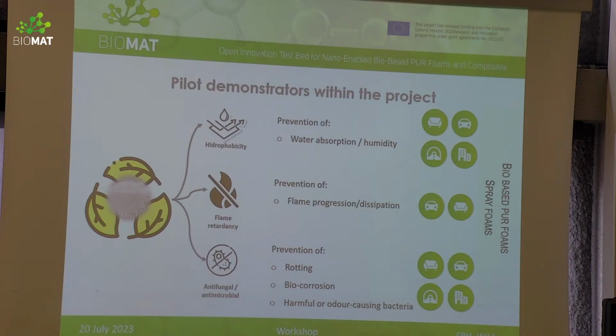Within BIOMAT, we have been using our particles in the production of different demonstrators that can find application in those sectors that you can see on the right of the slide in green circles. Specifically, we use hydrophobic particles to prevent water absorption and humidity. The flame retardant particles are used to prevent flame progression, and the antimicrobial particles to prevent rotting, biocorrosion, and the growth of harmful or odor-causing bacteria.